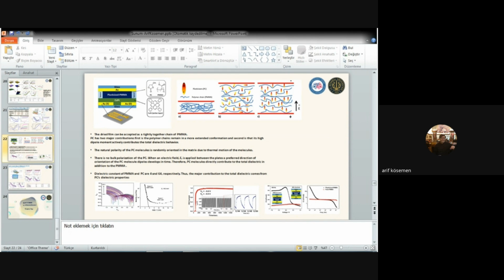And here you can see the electric properties of the plasticized PMMA. We also conducted an experiment under cryogenic conditions, from low temperature to high temperature, and we got the activation energy for the interface of the active layer and the propylene carbonate polymethyl methacrylate.